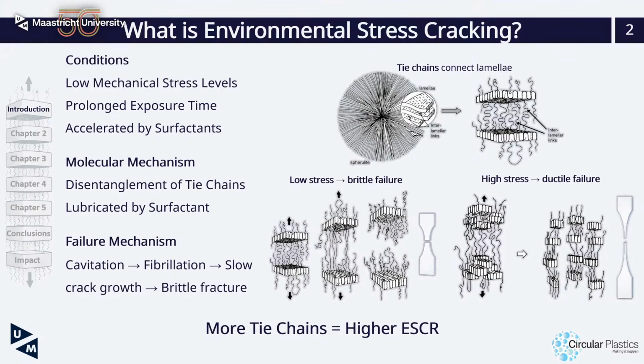Under low stress, however, the situation is a bit different. The stress is not high enough to break those lamellae, and instead the connections between them, those tie chains, gradually disentangle if we give it enough time. As a result, the material can develop cracks without large deformation, which is known as brittle failure.